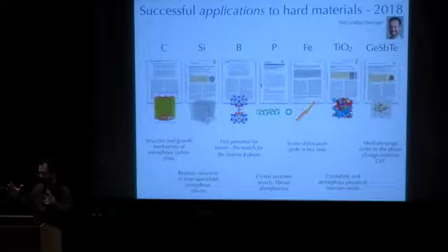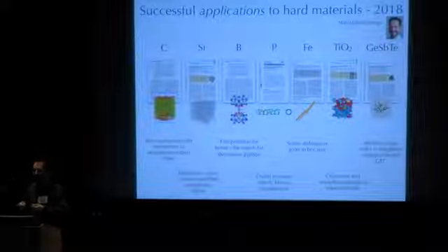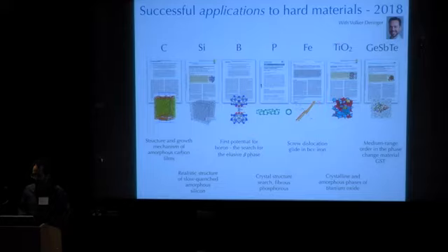We start with random, placing the atoms randomly. We train a crude model. We start quenching it. It's complete garbage, but we keep reevaluating small systems, 100-atom systems. We keep reevaluating the reference and keep improving the model until the quenches don't change. And I think 4 or 5 of these papers have that protocol in them.